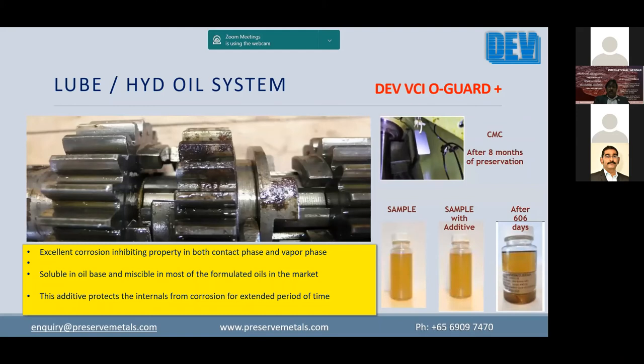Similarly, another system where we recommend such an additive is lube oil and hydraulic oil systems. As we know, where the oil is in contact with the metal surfaces, we rarely see corrosion problems. But corrosion comes in two other locations: the aerated surfaces and the tank bottoms, where water condenses from the moist air breathed in and out with day temperature variations. Those condensations settle down at the tank bottom and initiate corrosion of the tank bottom.